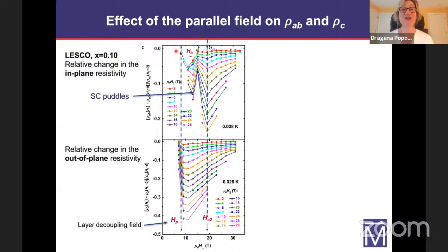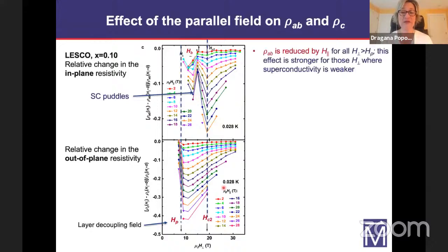So basically what we see is that the parallel field always reduces the in-plane component. And this is the opposite of what we would expect if the dominant effect of the parallel field was to break up the Cooper pairs. And in fact, if you look here, this effect of the parallel field is stronger in the region where superconductivity is weaker. So it seems that the dominant effect of the parallel field is not related to superconductivity.